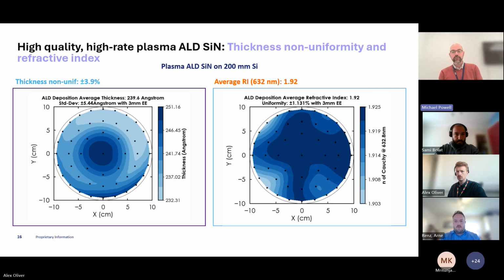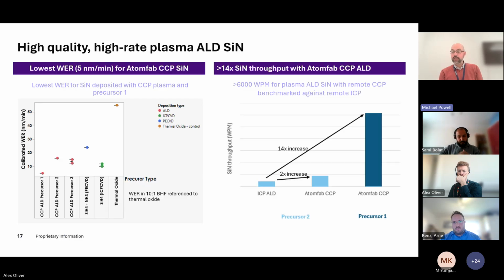You can change the RI in CVD, but what you're actually doing is playing between the silicon and nitrogen ratios in the material. So this is a stoichiometric silicon nitride film, and it's giving a stoichiometric silicon nitride RI value. And if we go to the next slide, we have also been able to show that the choice of precursor is really key. I can't give any details away about the precursor, but by changing our precursor, we were able to both increase our throughput and really improve the quality of the material.